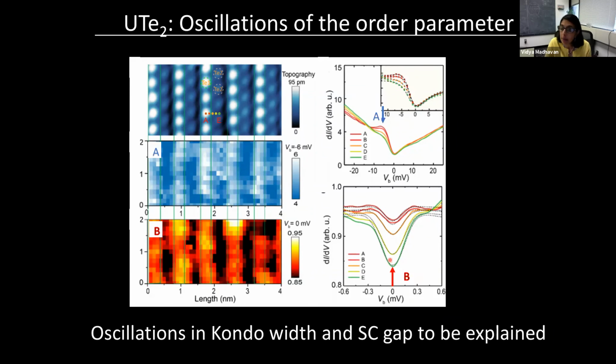It does disappear at TC, and it does disappear at HC2 for this sample. So it's sensitive to magnetic field and it's sensitive to temperature. So I would say that this feature here represents the superconducting gap with some matrix element effects probably, which might be causing this kind of spatial variation. That's entirely possible. We don't know yet.